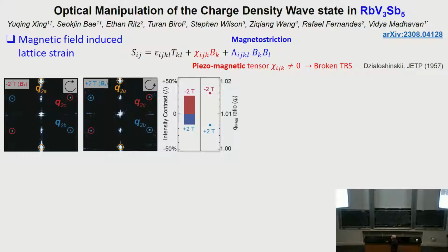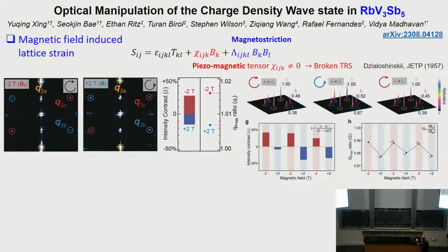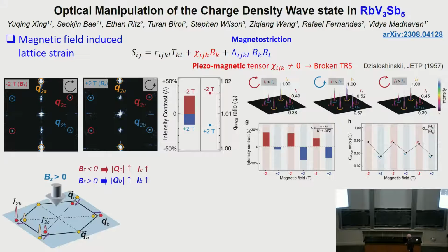And indeed, she finds that with a 2 Tesla field in the minus direction or plus direction, you see that the lattice responds exactly in the opposite direction. And that says this term is non-zero. Okay? And this can be repeated with different field directions. You also switch this sense of handedness, right? And maybe it's illustrated here. If Bz is greater than 0, these two ends go in, these two sides go out, right?